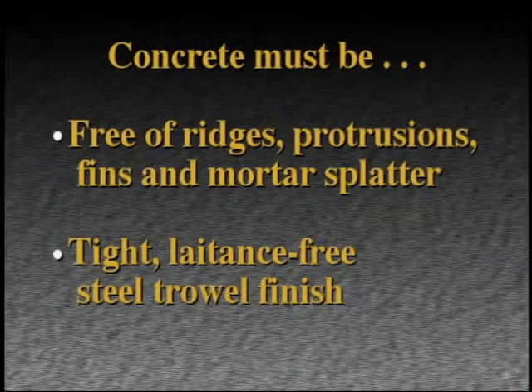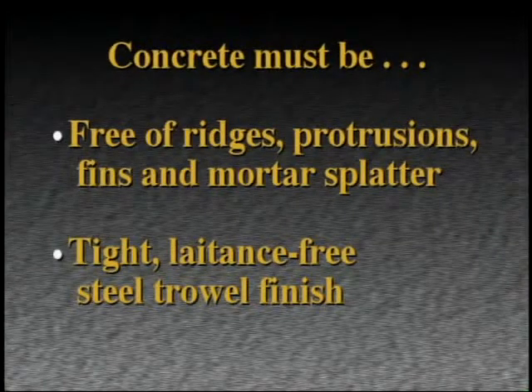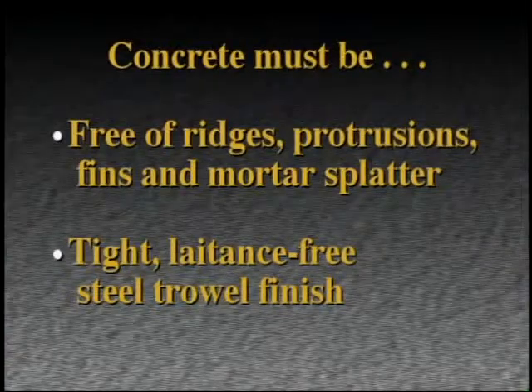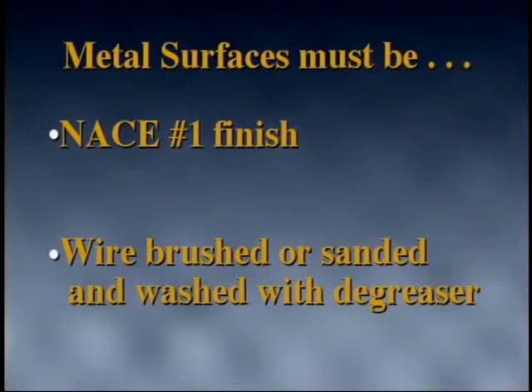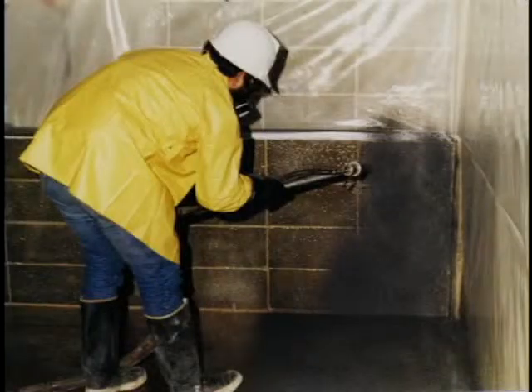Finished concrete substrates must be free of ridges, protrusions, fins, mortar splatter, and have a tight, laitance-free steel trowel finish. Abrasive grit blasting or acid washing are recommended for removing loose surface latex. A finish similar to the profile of 100 to 120 grit sandpaper is suggested. Metal surfaces should be grit blasted to an NACE number 1 finish. When this is impractical, clean by wire brushing and wash with a degreasing solvent. Surfaces not scheduled for coating should be protected against overspray.